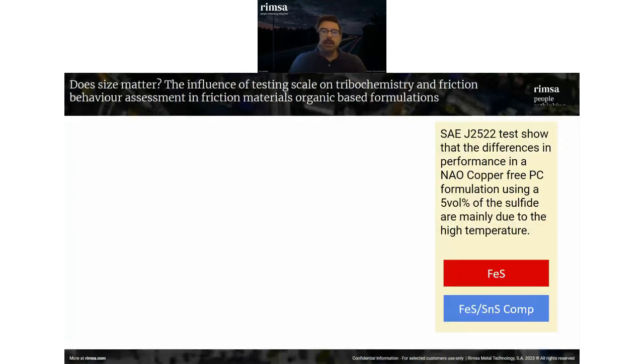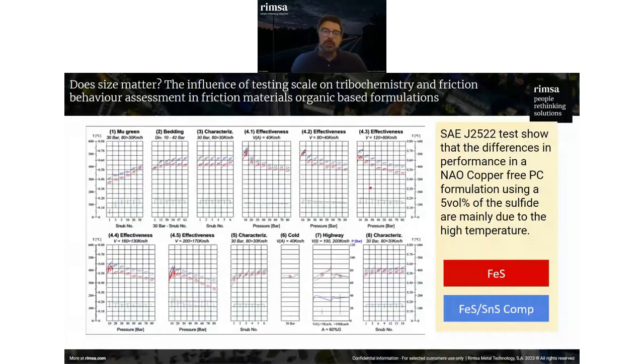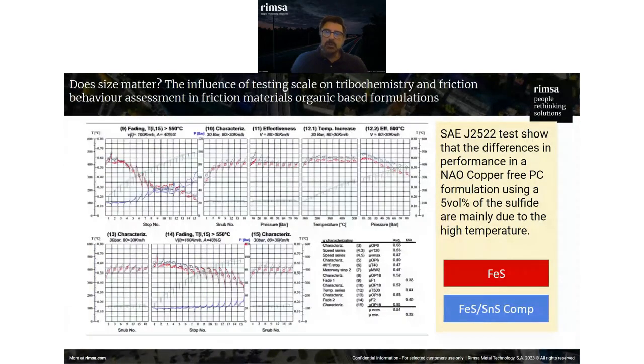And we are testing these two different additives in the same formula. So we are making two different friction materials where everything is the same except the sulfide used. In this case, we are using 5% in volume of the iron sulfide or the composite, the SFO5, iron sulfide, tin sulfide composite. We see the difference in coefficient of friction; these are the results of the full-scale dynamometer. So this is the real test. It's not really different, especially at high temperature. The response of using the iron sulfide or the composite in this particular formula, the engineering results, is basically the same. So we have basically the same coefficient of friction.